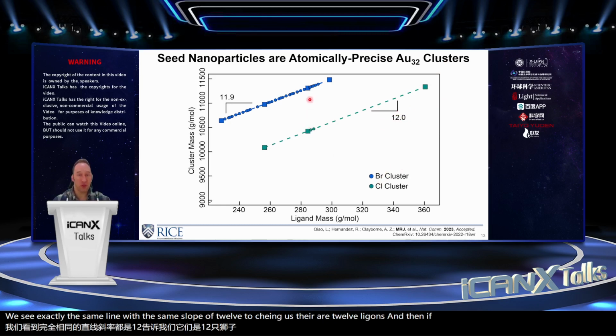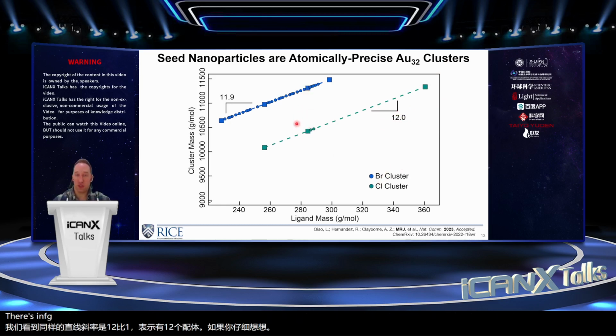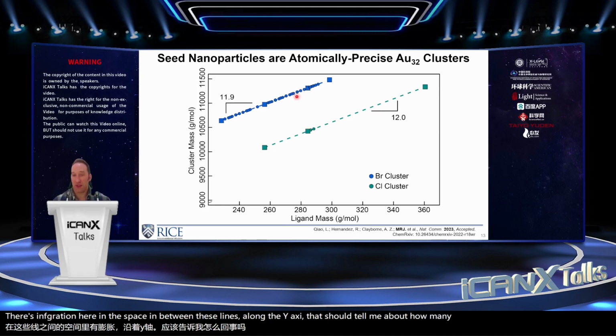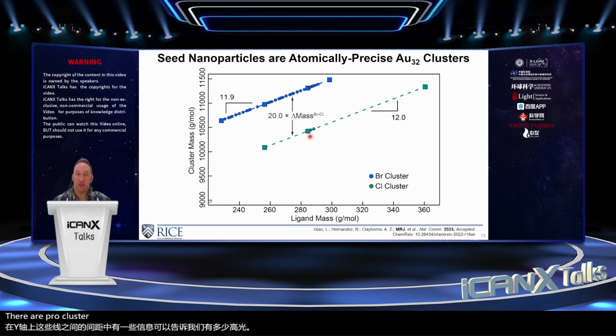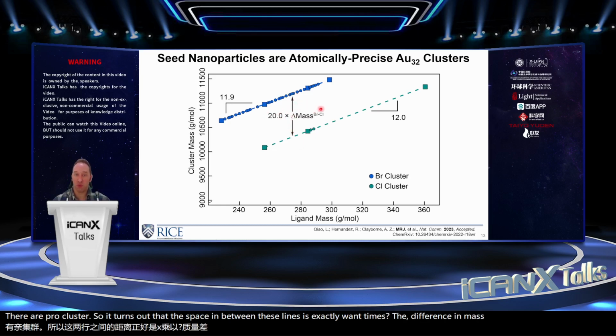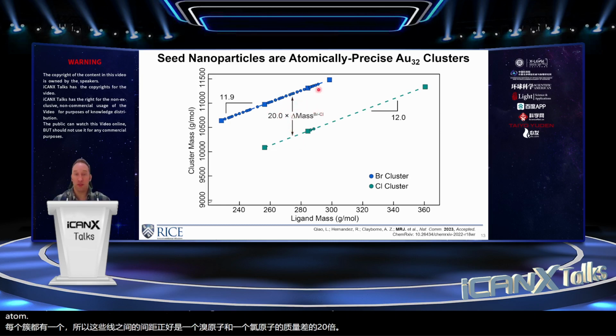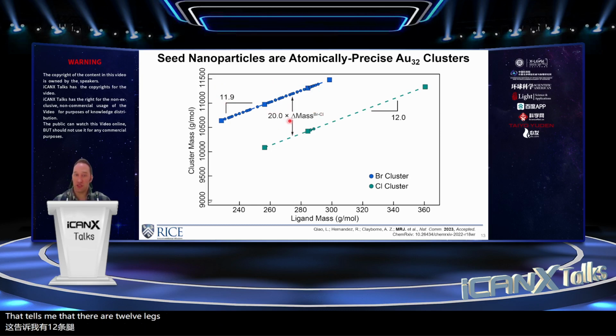And then if you think about it, there's information here in the spacing between these lines along the y-axis that should tell me about how many halides there are per cluster. So it turns out that the spacing between these lines is exactly 20 times the difference in mass between one bromine and one chlorine atom. So that tells me that there are 12 ligands, 20 halides.